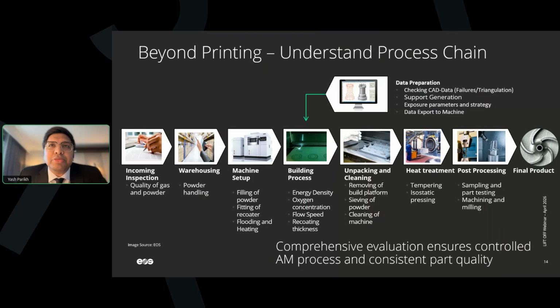Most of the time, the post-processing steps are the most important factor to the final performance of the part, because they are derived from the welding and casting literature, and it does not do justice to the laser powder bed fusion made part. So there is that. The fatigue behavior changes significantly if you have a different surface finish on those parts which are off the build plate. Go to the next one, please.